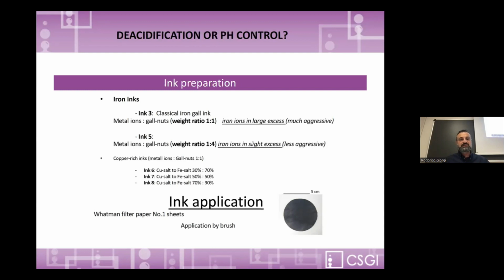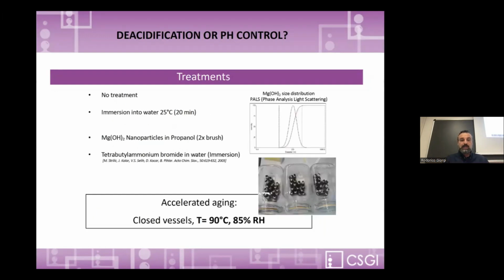And we also prepare a set of inks where we have a different ratio between iron and copper, because in many cases we have the presence of copper, and in some cases this is in very relevant amounts. Then we apply this type of inks on Whatman paper that is pure cellulose, no sizing. This means that the ink is even more aggressive for cellulose, because cellulose is naked and has no protection in any way.